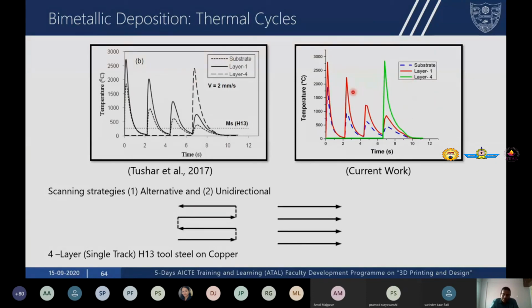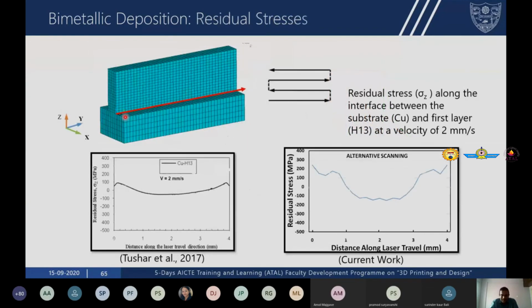You can clearly see that the results obtained from our computational models are in good agreement with what's already published in the literature. So this shows that the models are giving information that is not only useful to understand the physics happening in the process, but you're also able to obtain valuable insights about temperature, residual stress, thermal cycling, cooling rates, and thermal gradients. And this is the residual stress at the interface between the copper and H13 steel obtained from the published paper, and these are our results for an alternate scanning strategy.